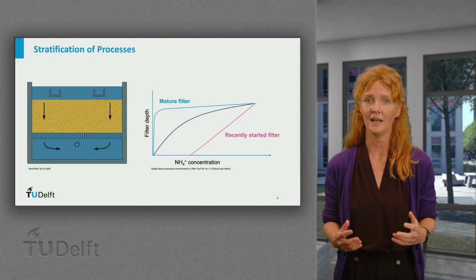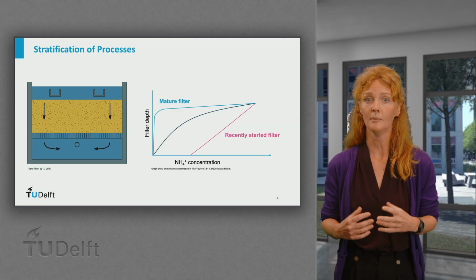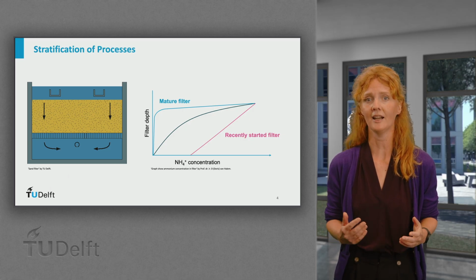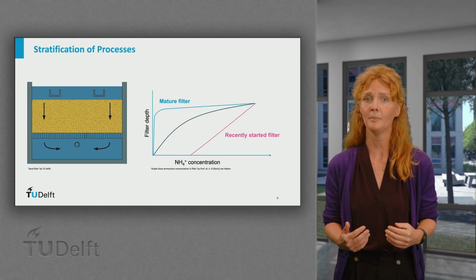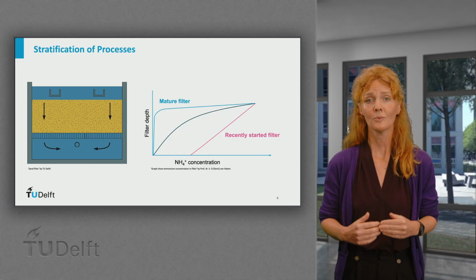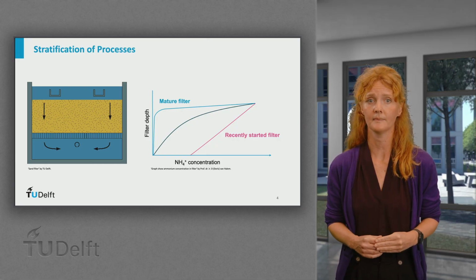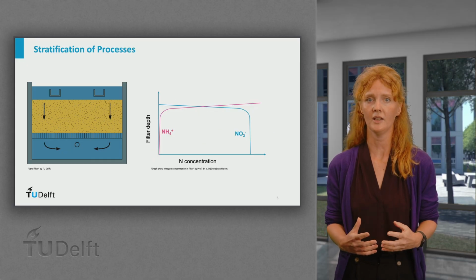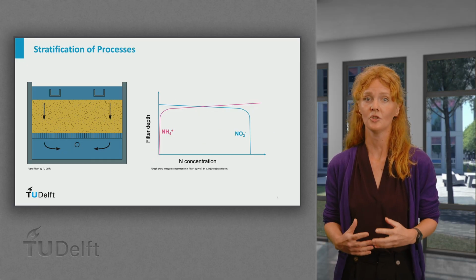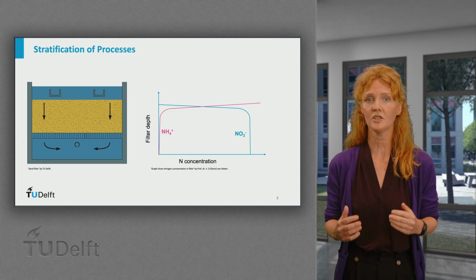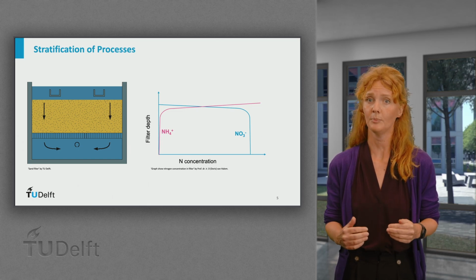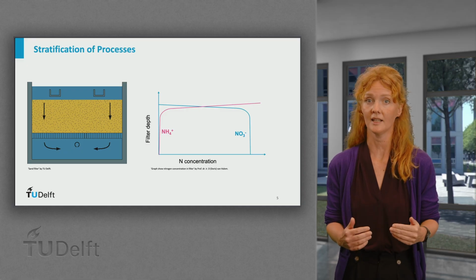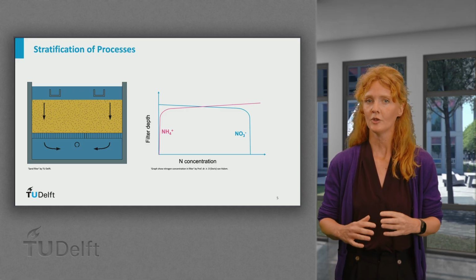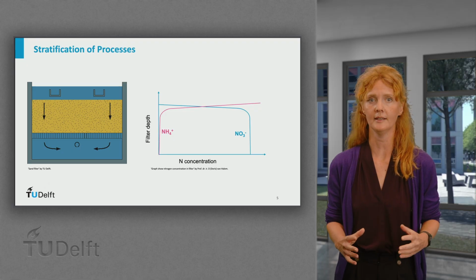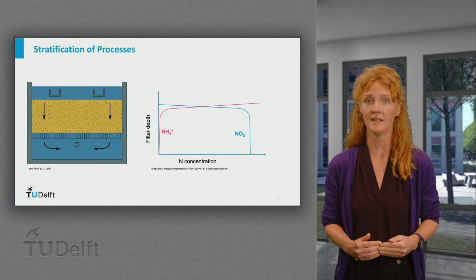If we look at the nitrogen balance over the height of the filter bed, the ammonium will initially be removed over the complete height of the bed. But with time, the biofilm will concentrate in the top layer, resulting in a stratification of processes. In a steady state situation, ammonium will be oxidized to nitrite in the top layer, after which nitrite is converted to nitrate, deeper in the filter bed. Also, direct nitrification has been observed in filters, so in any case, in a good functioning filter, nitrate will be the only nitrogen species detected in the produced water.